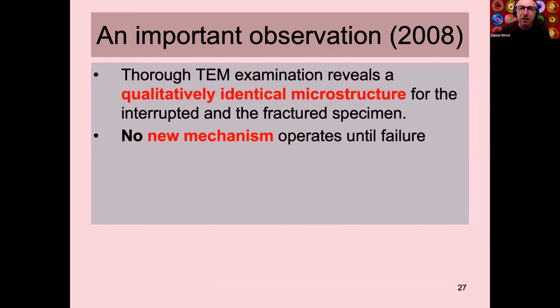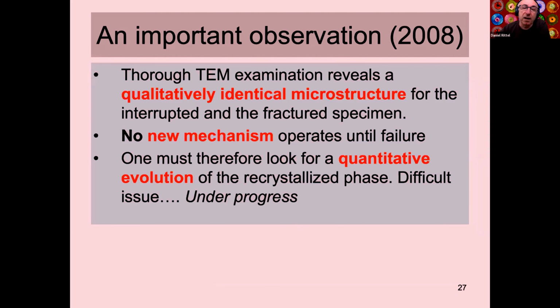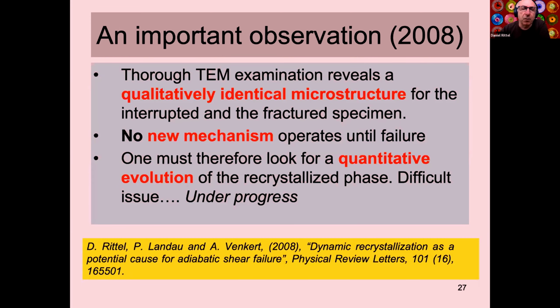There's no new mechanism that operates until failure, and one should therefore look for a quantitative evolution of this recrystallized phase. That's a little bit difficult. That's work in progress for the past 10 or more years. So here we reported that result as blaming dynamic recrystallization as a potential cause. Because in fact, if we're looking for a microstructural softening mechanism, this is your softening mechanism. It's not thermal, it's microstructural. So if you can control it, you can control the propensity to dynamic failure.